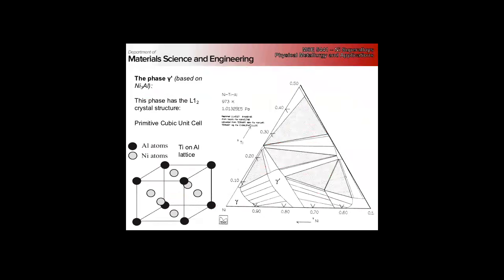And if we look at the ternary now, this is at 973 Kelvin. This is the two-phase region that we're mostly going to be interested in - gamma out here, gamma prime. And you can see that most of the titanium and aluminum are going to tend to segregate to the gamma prime.